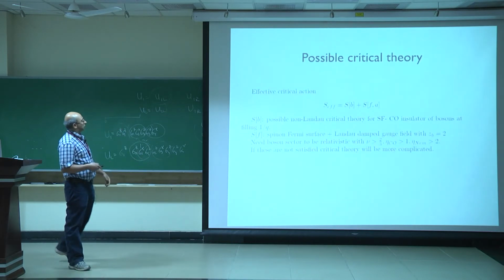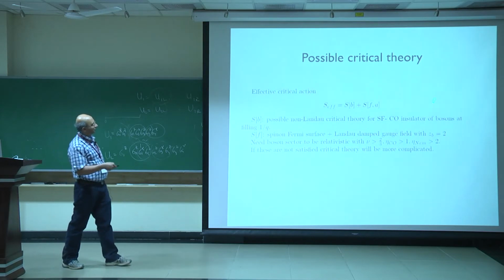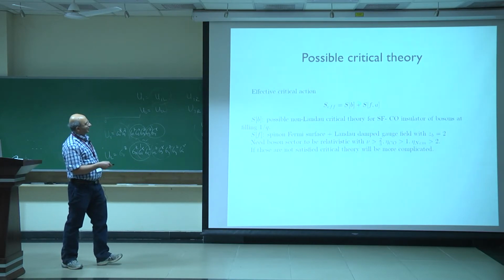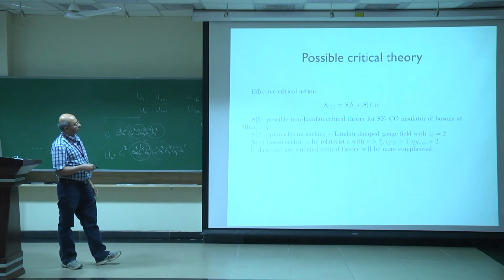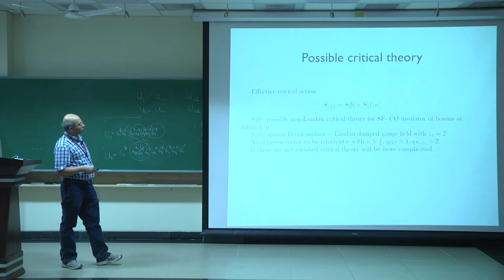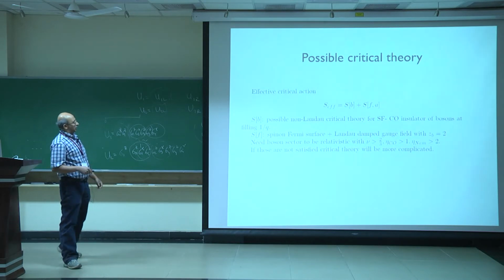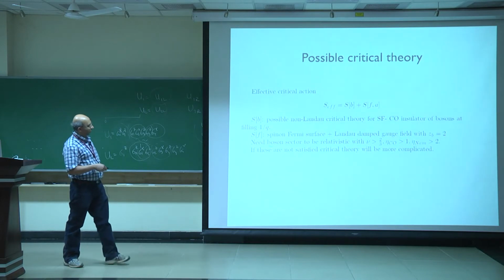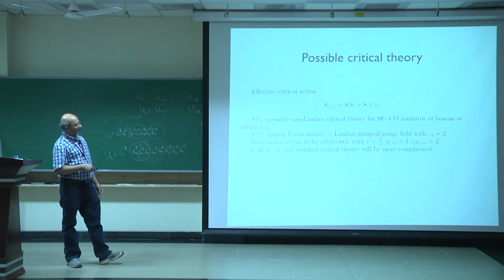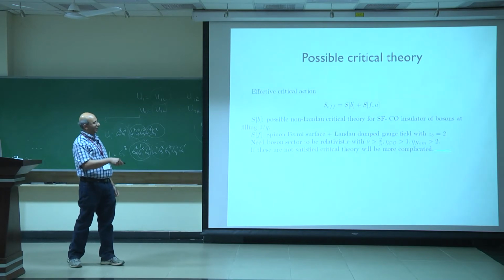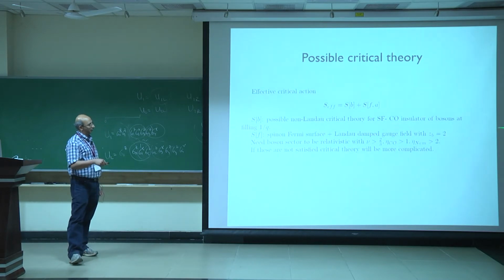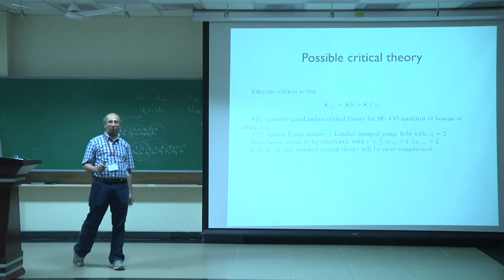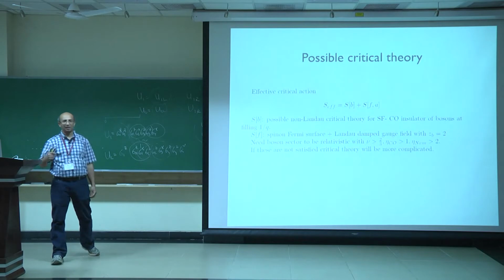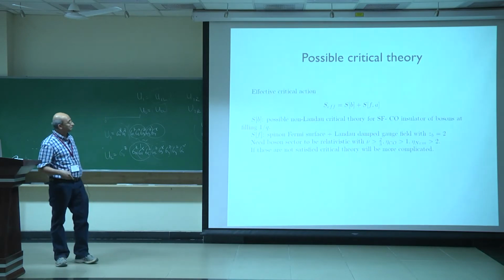Okay? So an effective critical action then will take this form, where S of B is this possible non-Landau critical theory for the superfluid to charge ordered insulator transition of bosons at filling 1 over Q. And this is the standard spinon Fermi surface coupled to this z equals 2 Landau damped gauge field. For this kind of story to work, the criterion is that the boson sector needs to be relativistic with exponents that satisfy these inequalities. If these inequalities are not satisfied, then the critical theory will be more complicated, and we have to do a hell of a lot more work to figure out how this transition goes.